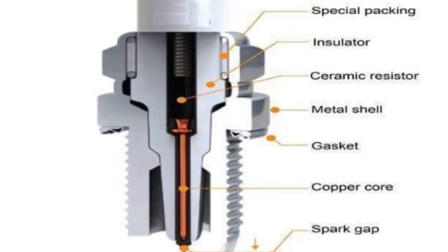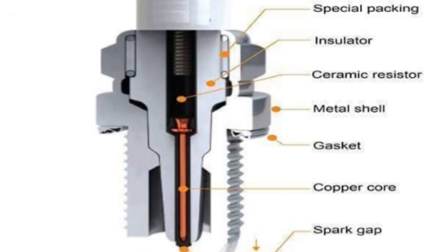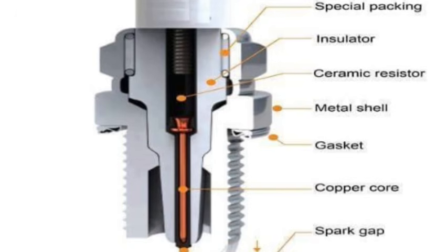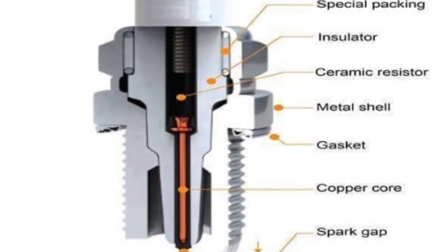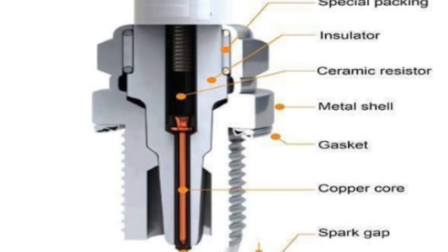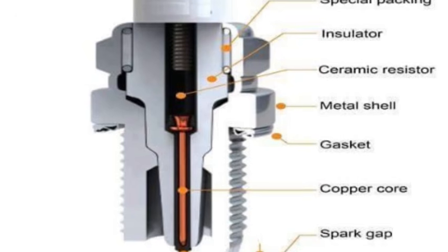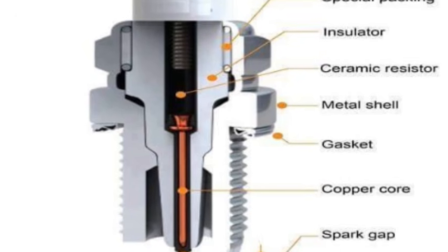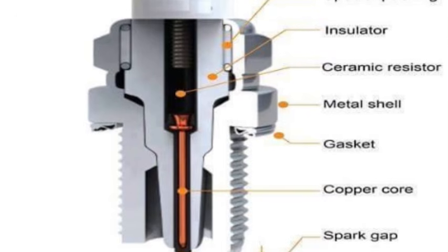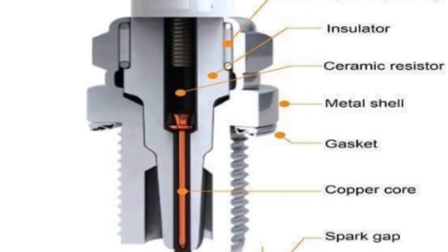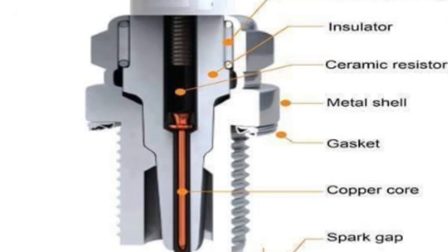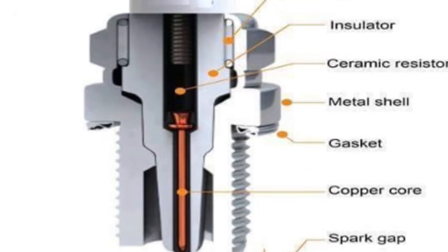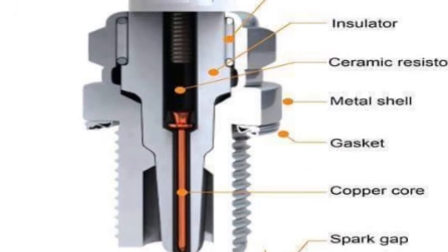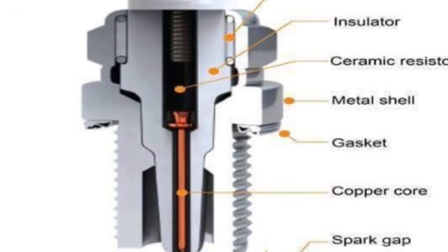This happens in a radial aircraft engine at full power, roughly 50 times every second. The spark plug must survive this, hour after hour, without the ceramic insulator cracking from thermal shock, without the electrodes burning away, without the assembly overheating to the point where it glows and ignites the mixture prematurely. And it must do this while staying within a narrow temperature band.